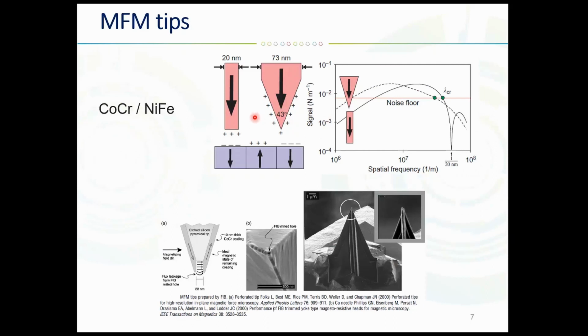These are some of the interesting specifics about how magnetic force microscopy works. First of all, as I mentioned, we need to have a permanent magnet at the end of an AFM tip. These days, this is done by coating a ferromagnetic material, effectively a permanent magnet, at the end of the tip. This is usually a combination of cobalt chromium, or sometimes nickel iron. You can purchase these MFM tips off the shelf from many vendors, with different amounts of permanent magnetic moment. You can get them in low, medium, or high values of magnetic moment or coercivity of the tip. It depends on your application.